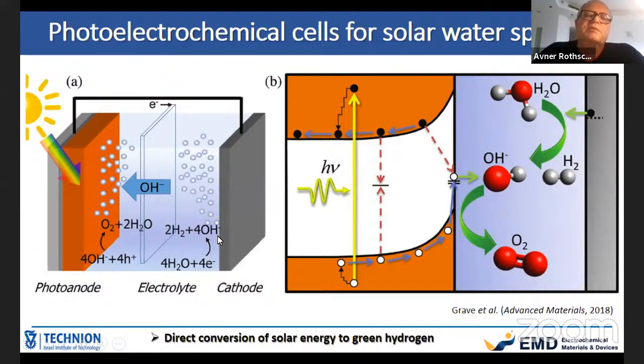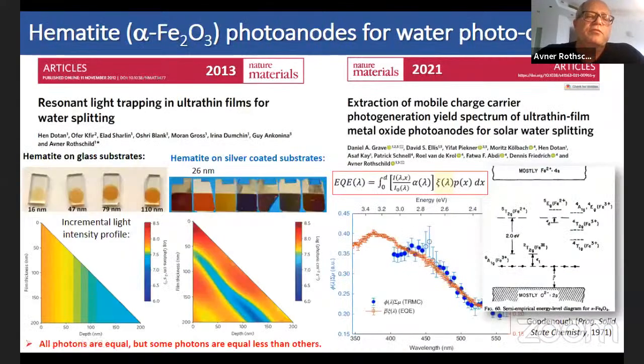So that is the concept. And for the last more than 10 years, I've been working on a specific material, a form of iron oxide called hematite. That's the chemical composition that is apparently suitable in many senses. It is stable in alkaline solution, it absorbs visible light, and it is a cheap material that is also photoactive for water photooxidation. The main issue with this material, at least that's what we thought until not so long ago, is that the electron and hole recombine very fast in this material.